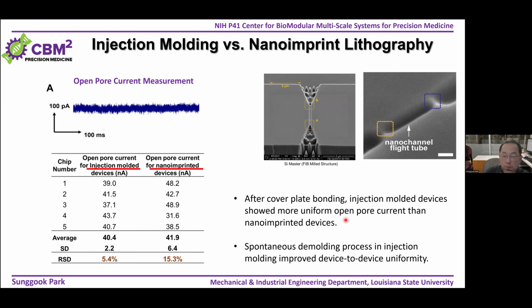Also, one of the things we can do to check the uniformity of your device is, after you fabricate the nanofluidic device, you put on the cover plate, fill your nanofluidic device with a salt solution, and then measure the current, which is called the open pore current. So we produced several chips from the same mold insert, one made by injection molding and one made by nanoimprint lithography. For those devices, we put the cover plate on, fill with the electrolyte solution, measure the open pore current, and see how uniform those currents are.